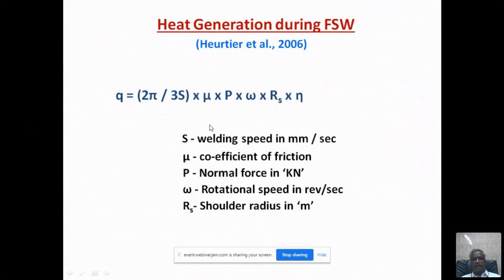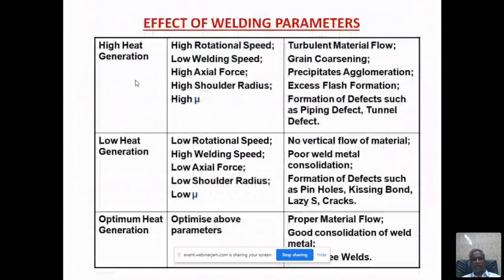So if you look into this, S is the welding speed, mu is the coefficient of friction, P is the axial force, omega is the rotation speed, and this is the shoulder radius. So out of all the parameters, the welding speed, which is in the denominator, has an inversely proportional relationship with the heat generation. All other parameters are in the numerator, so they have a directly proportional relationship with the heat generation. If these parameters are higher, then the heat generation will be higher. If these parameters are lower, then the heat generation will be lower. But for the welding speed, it is opposite. If welding speed is faster, heat generation will be lower. If welding speed is slower, heat generation will be higher, opposite effect. So based on this, in this process we need to optimize the parameters.